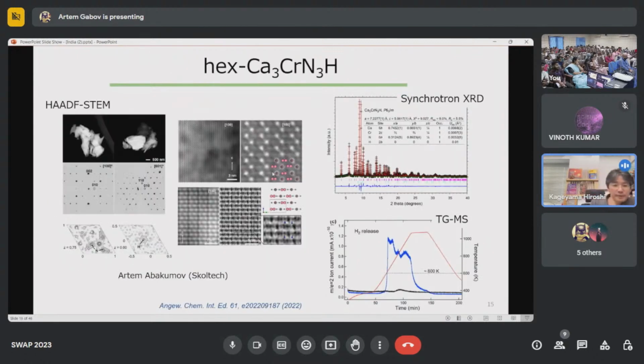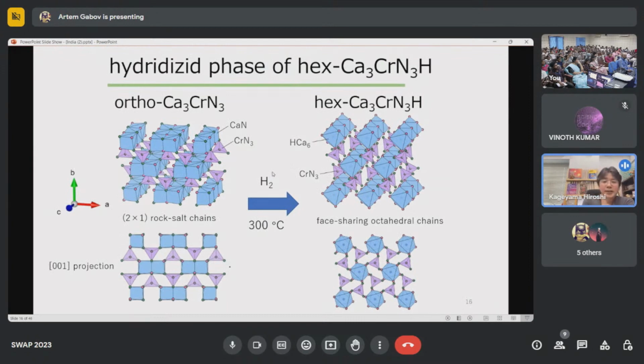Then we collaborated with Artem Abakumov, who is an excellent expert in transmission electron microscopy and structure analysis. And we found out that the crystal structure looks like this. Okay, we used TEM and synchrotron and neutron diffractions, and we solved the crystal structure. And we found that hydrogen is also included in the structure. So it is a hexagonal phase. It's not a nitride, but a nitride hydride. Okay. Then this shows how the crystal structure has changed through H2 annealing. Then we found the relation between these two structures.